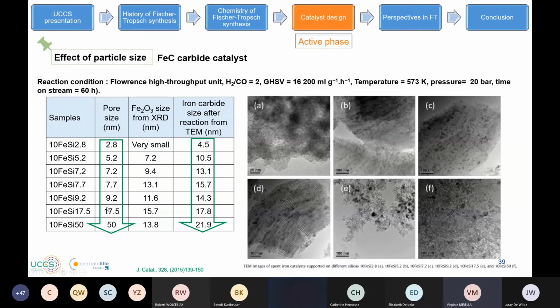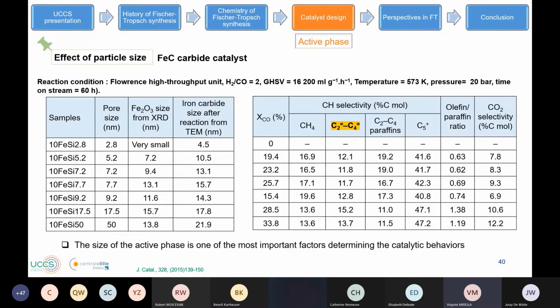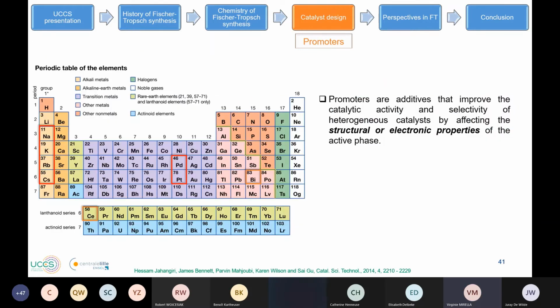So here we have an increase of the pore size and an increase of our carbide phase. In reactivity, we observed a high conversion for the catalysts that exhibit the larger particle size. And when we focus on the selectivity, we also observe high selectivity with the catalyst that has large particle size. So we also conclude from this study that when we have small particle size, probably we have less extent of carbidization, and when we have large particle size, we probably have better extent of carbidization that leads to high selectivity in olefins.